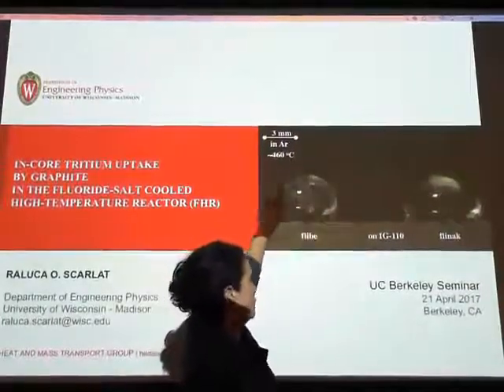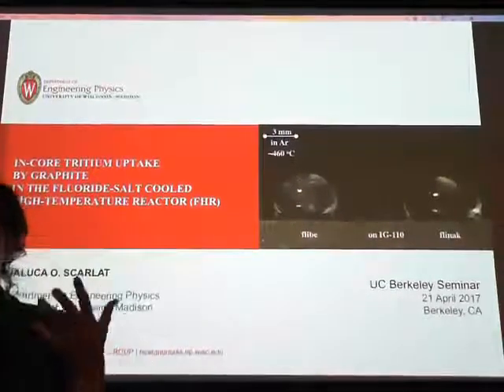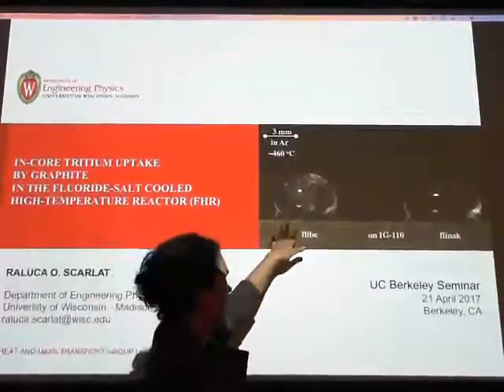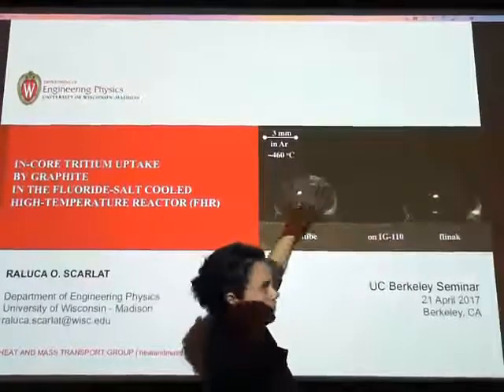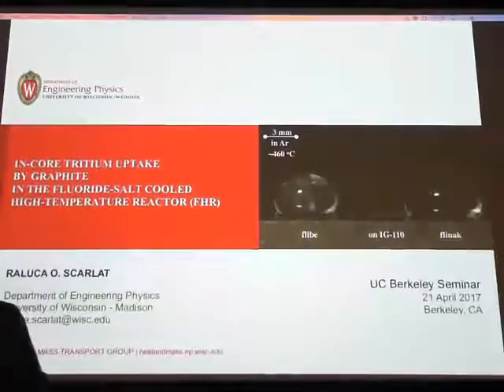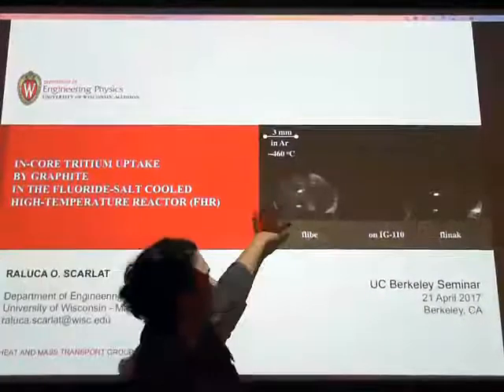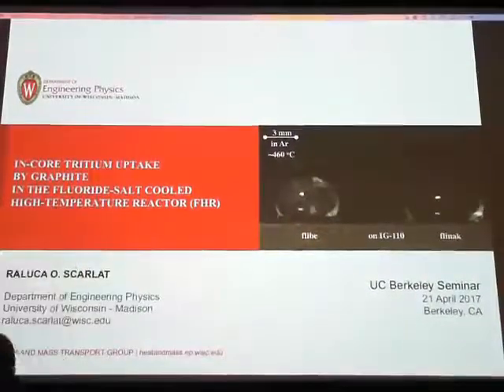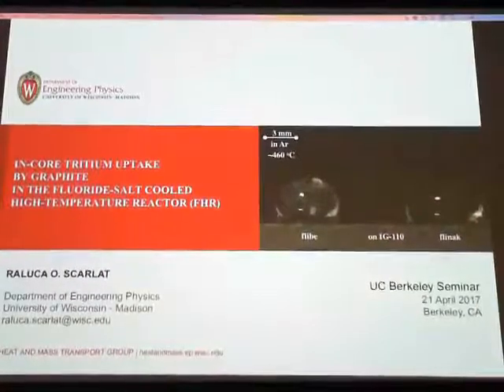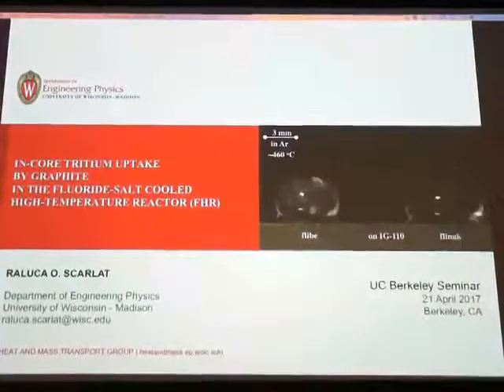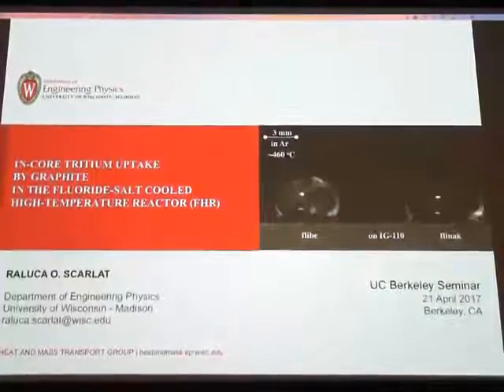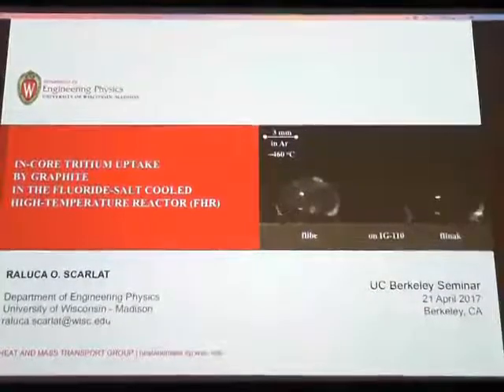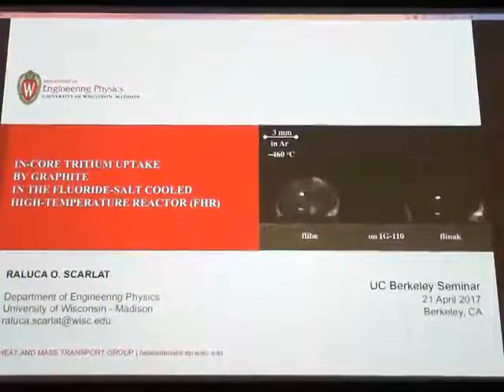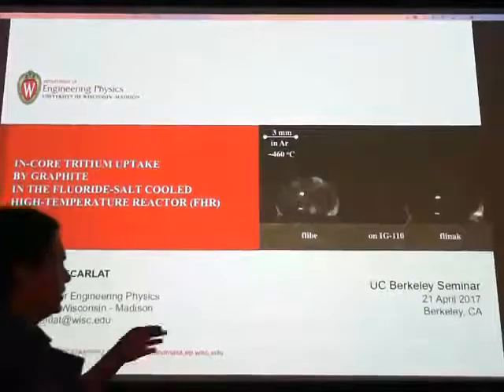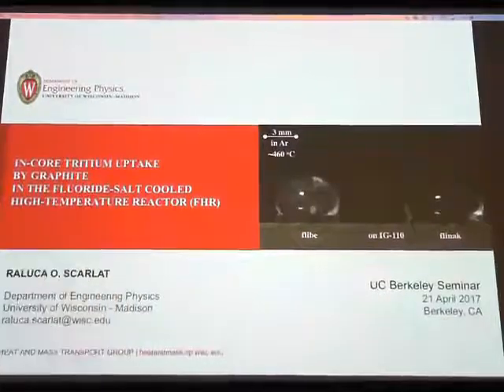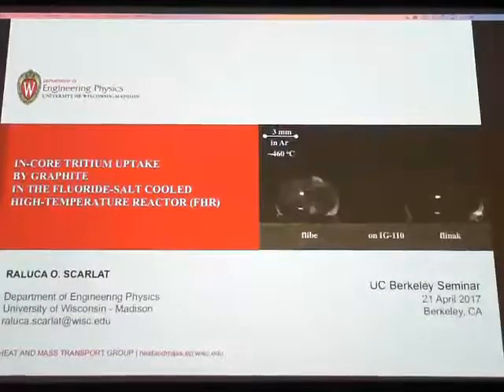What's happening here is that the surface of the droplet is radiating out to a colder lid, and the bottom of the droplet is hot, and that very small thermal gradient is creating a recirculation within the pebble. What's also remarkable is that you see this skin that's forming, and that's the frozen liquid that's melting and freezing and melting and freezing. And so these are some of the problems that I study. How do isotopes transport between phases, between liquids and solids, and between gases and liquids and solids as well? It's harder to see, but there are bubbles in there as well circulating. So we'd like to know how isotopes transport.